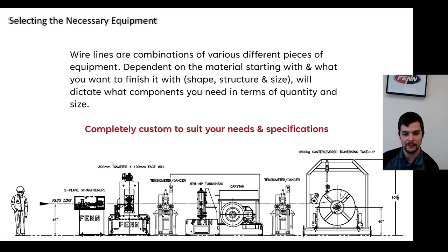We then ran it over this combination dancer tensiometer for the smaller wire. It used a dancer for the larger wire. It used this tensiometer pulley up here. It then ran through a Turks head on a pulling capstan. The Turks head shaped it to its finished profile while being collected on the capstan to pull it through for back tension. And then it threaded through another dancer device for speed and tension control as it then collected onto this take-up reel for collecting the finished product.